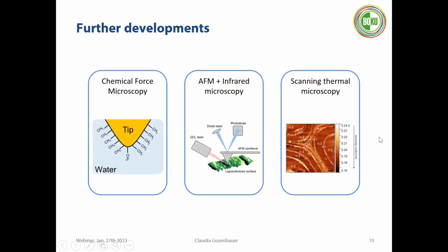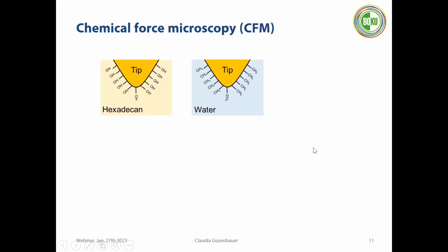And I said before that with our AFM measurements, we tried to fill the gap between high resolution microscopy and also chemical mapping. And here we have further developments that we applied on wood materials to kind of fill this gap. One of them is chemical force microscopy, where we chemically modify the tip. Then there's a lot of research going on at the moment with combining AFM with infrared microscopy. And also we applied scanning thermal microscopy. So first I want to talk about chemical force microscopy.